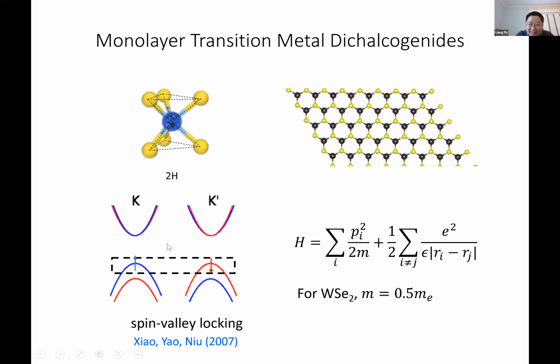At low density, when we dope the material into the valence bands, the effective Hamiltonian for the doped holes is very simple. It consists of the kinetic energy, which is just p squared over 2m, because the bands near the valence band top are parabolic, and these holes interact with each other through the Coulomb interaction, so it's e squared over r. In this case, because of the spin-valley locking, there are only spin or valley degrees of freedom, but not both. So in terms of the number of degrees of freedom, it's 2 instead of 4.